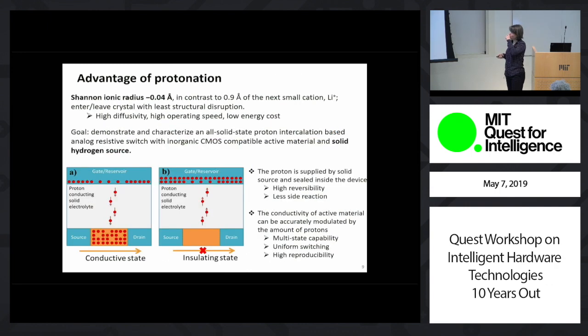And our goal is to continue with protons, although challenging as they are, because they pretty much present the smallest ionic radii among all the small cations that we can deal with, which means they should impart the least structural disruption, which is important for the stability of the material and the device. And again, due to that size, they have very high diffusivity, which would translate to faster operating speeds as well as lower energy cost. Okay? So the challenge is how can we come up with a solid state device that is proton-based? And for that, we must use a solid hydrogen source.